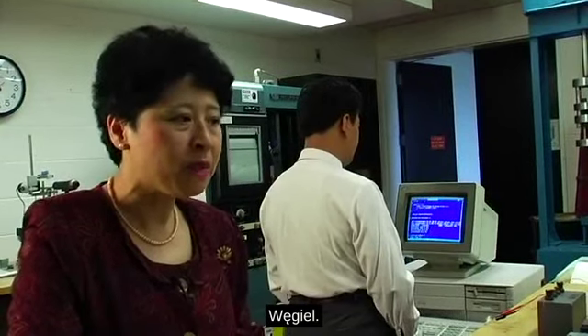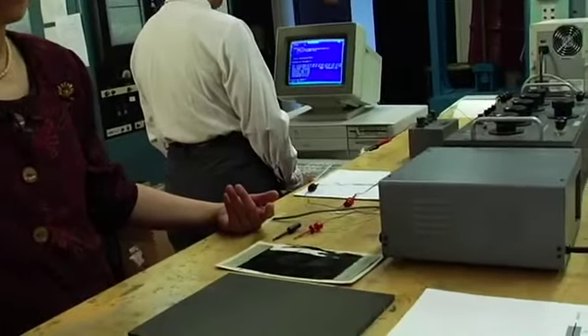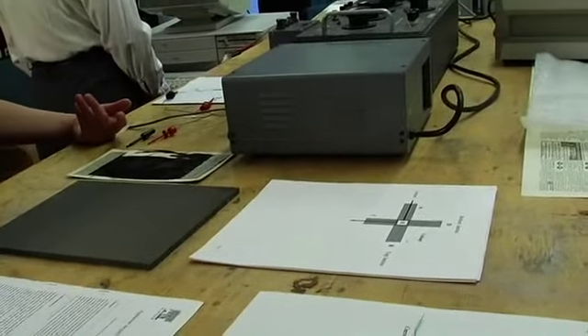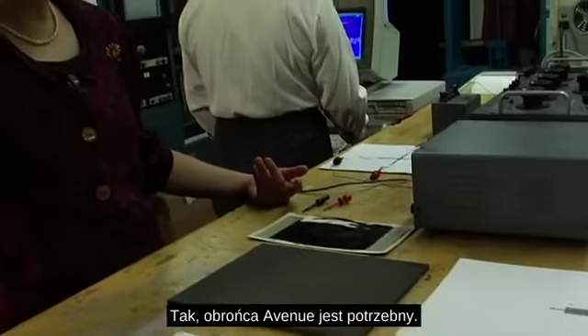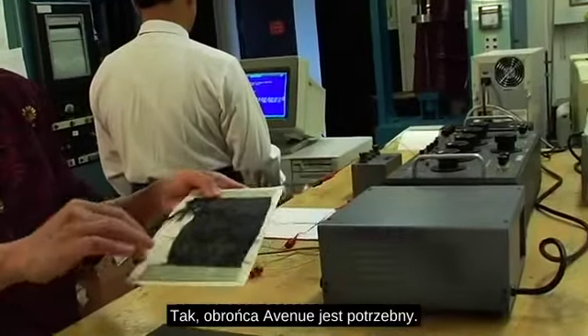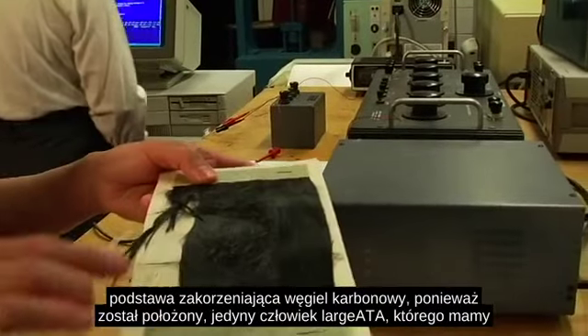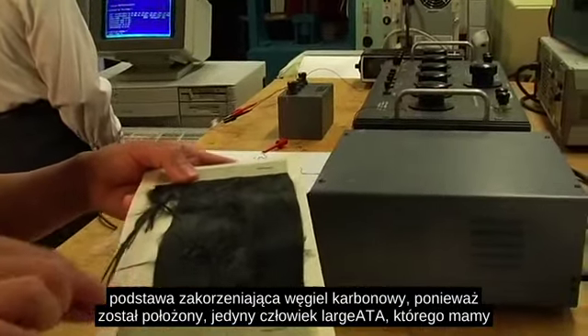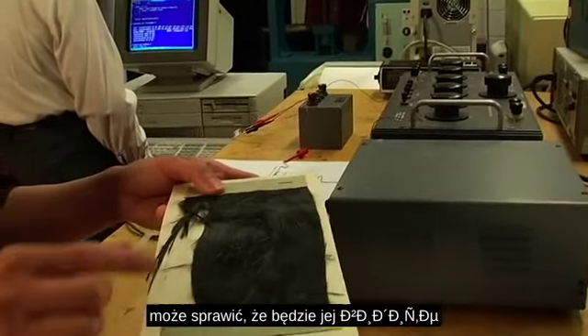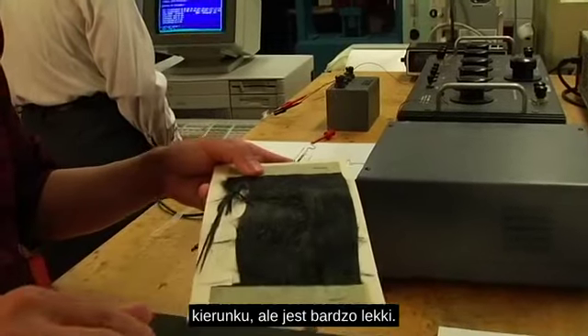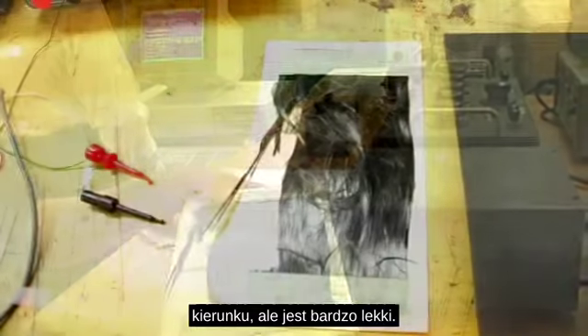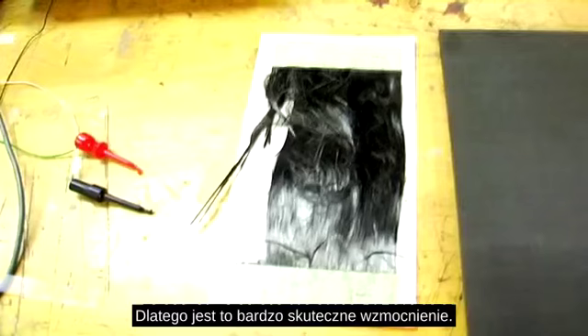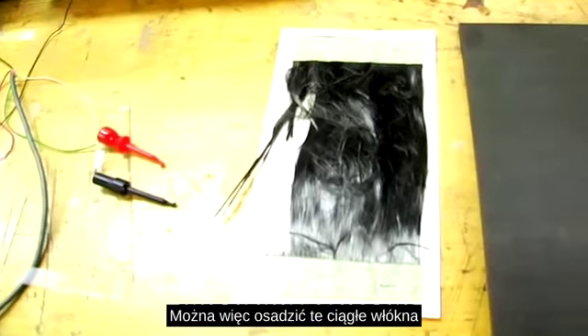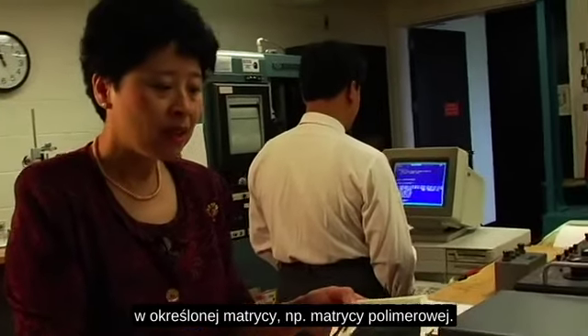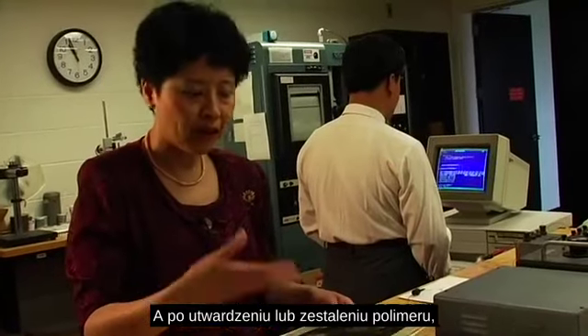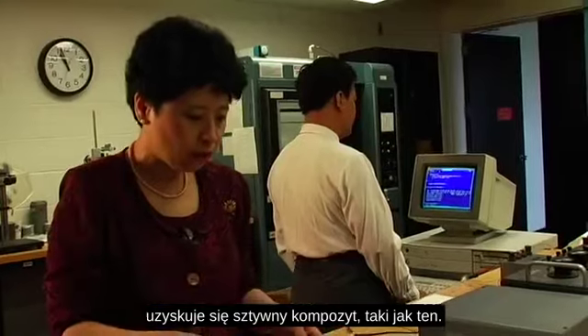Carbon fibers are most important from a practical point of view because of the carbon fiber polymer matrix composites. The polymer matrix is primarily epoxy. This is an example of the carbon fiber. It looks like hair, but it's just a very small fraction of the size of our hair. And it's all carbon. It is very strong and stiff in this direction, but it's very light. And so it is very effective as a reinforcement. One can embed these continuous fibers in a certain matrix, such as a polymer matrix, and after curing, or letting the polymer solidify, one obtains a stiff composite like this.